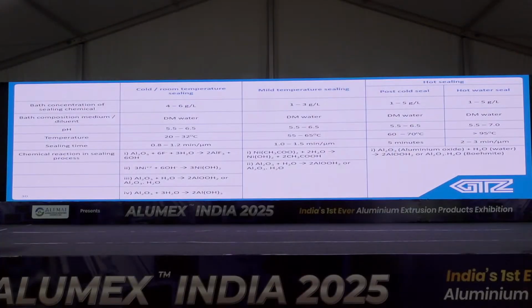Mid temperature sealing has only two mechanisms: nickel hydroxide formation as well as aluminum hydration or boehmite structure formation. So it is a little slower than cold temperature sealing. And in hot temperature sealing, only one mechanism is there, that is hydration of aluminum oxide and boehmite structure formation. So that's why hot sealing is slower, around 2 to 3 minutes per micron. Hot sealing is also done after cold sealing; time is not so important there, only 2 to 5 minutes is required for the post cold sealing treatment.